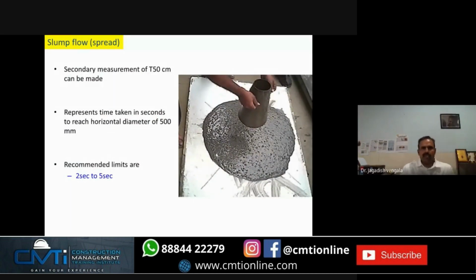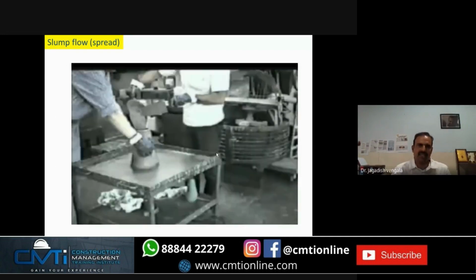And there is also one more measurement, what we call T50 centimeter measure. What does that mean? When you place the concrete in the slump cone, when you lift it, the concrete will flow. The time taken to reach the 50 centimeter circle or 500 mm spread, how much time it will take, that you measure, it should be generally between 2 to 5 seconds. Let us watch a video.